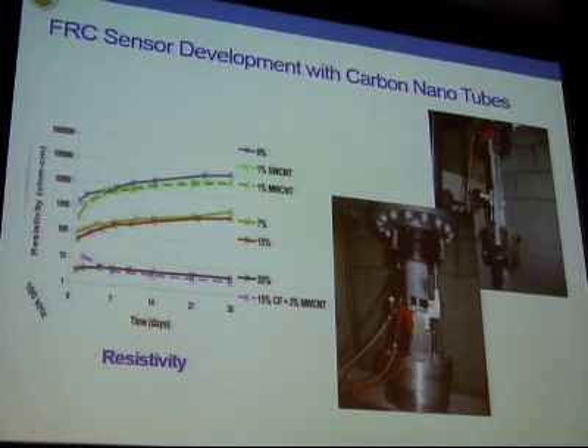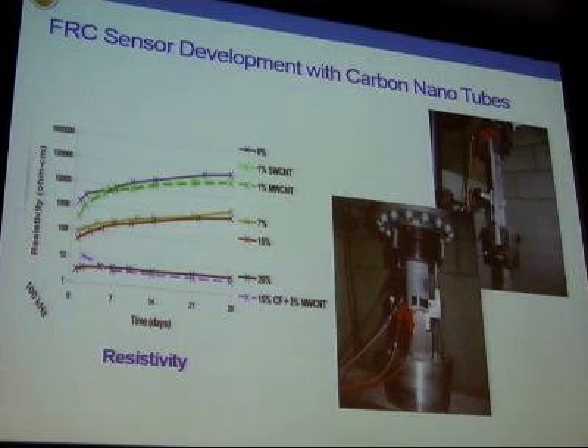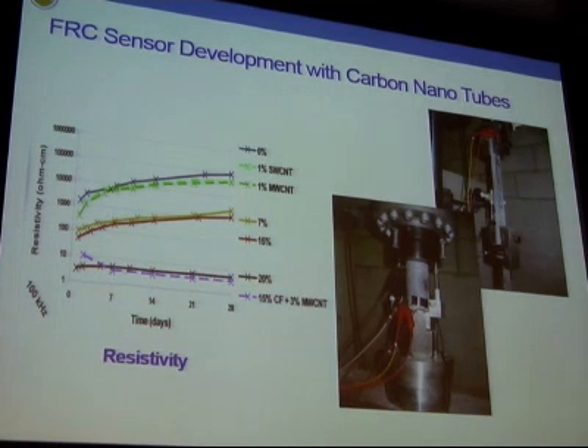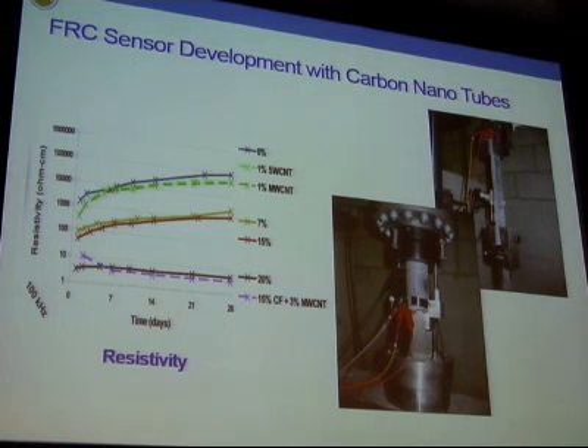So these are materials actually. You have these materials which have been stressed, and we're trying to generate a sensor out of these. And the sensor data is actually predicted using impedance. So these materials become highly conductive. And when you pass a current through that conductive material and put a stress on it, its impedance changes. What that means is if I have a material which has, say, multi-wall carbon nanotube, I have a material with a very high conductance or a very low resistance. And as I put a certain stress on it, that material becomes extremely sensitive because its impedance will change as a result of the change in the stress level, which is what we call piezoresistivity.